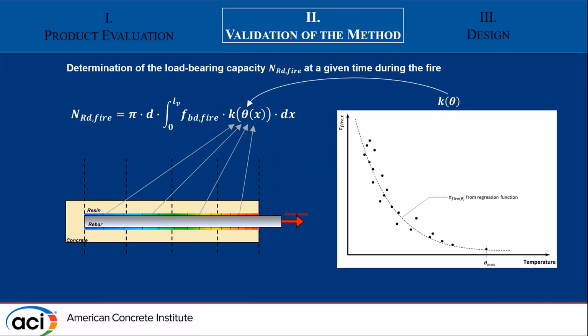Basically, we add up the contribution along the bond of each segment, which has a different temperature, after having calculated the temperature distribution along a bond in a building exposed to fire. This is what we call the resistance integration method. We validated this method using full-scale testing. The philosophy of this full-scale testing is we have a full-scale structure, we predict when failure occurs using the resistance integration method, and then we compare this to the experimental observation.